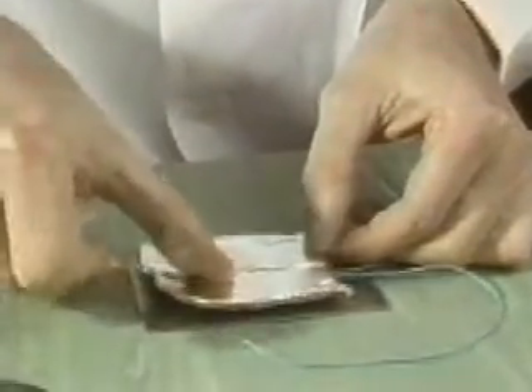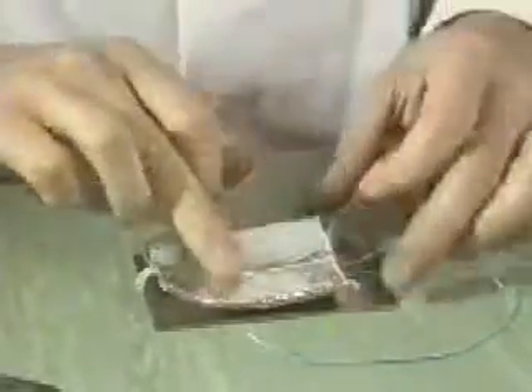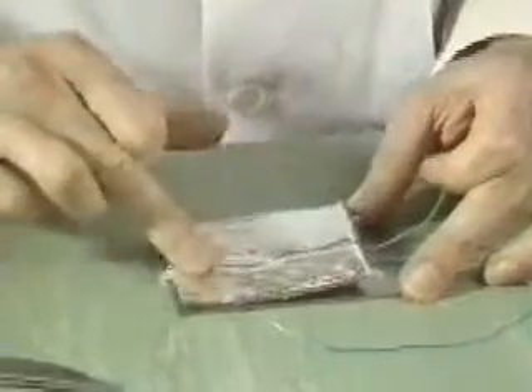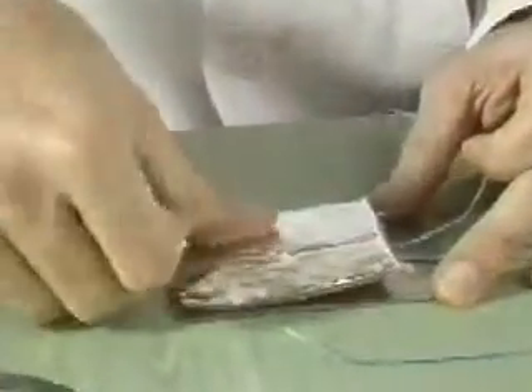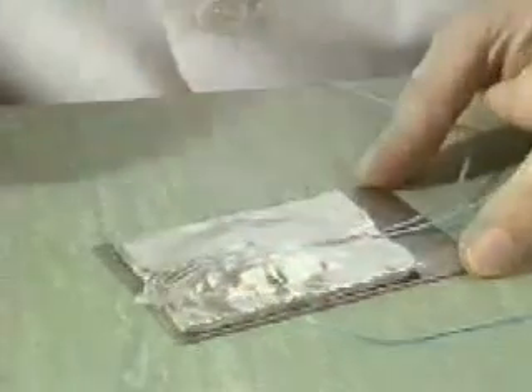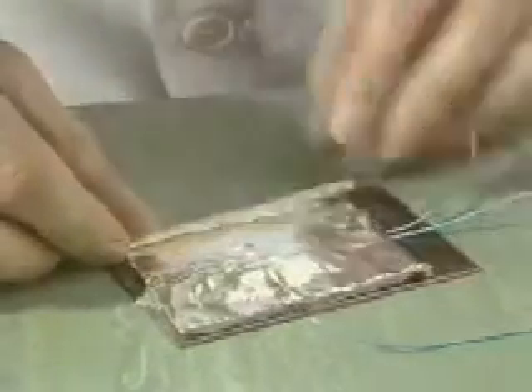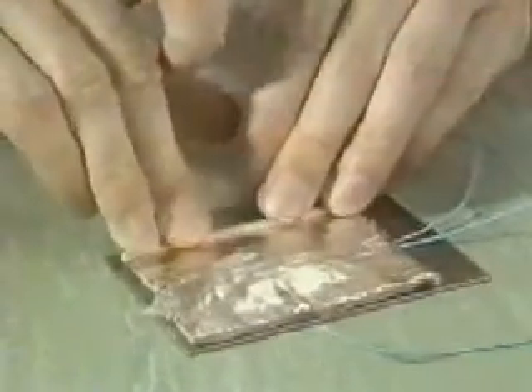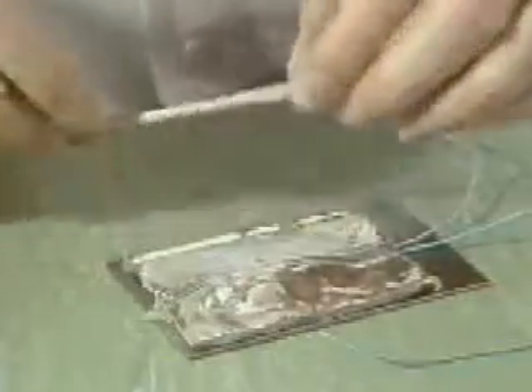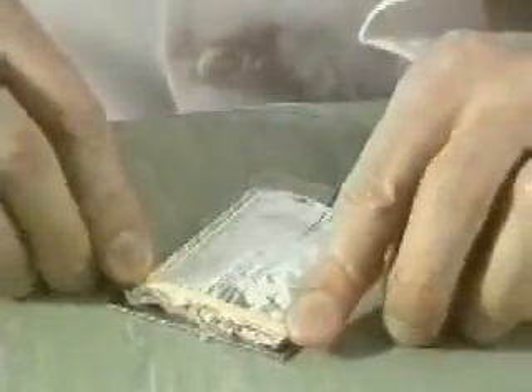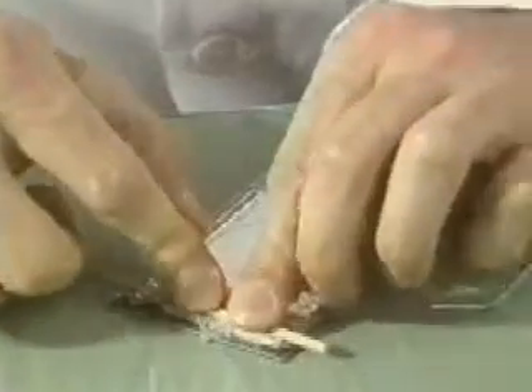No cavities should be produced, and the aluminium film should not be damaged. The aluminium film should be pressed as near as possible to the metal of the test object so that the diffusion of moisture into the measuring point at the edge is made more difficult. Here, this step is made easier by using a round wooden stick.